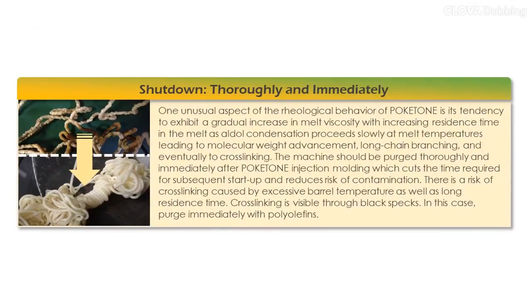One unusual aspect of the rheological behavior of polyketone is its tendency to exhibit a gradual increase in melt viscosity with increasing residence time in the melt. As aldol condensation proceeds slowly at melt temperatures, it leads to molecular weight advancement, long chain branching, and eventually to cross-linking. The machine should be purged thoroughly and immediately after polyketone injection molding, which cuts the time required for subsequent startup and reduces risk of contamination.